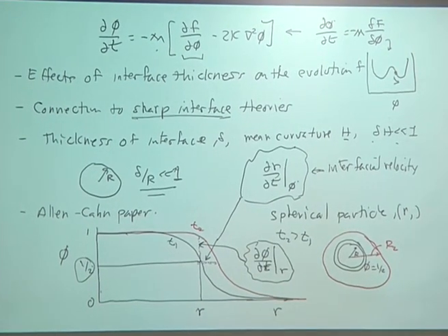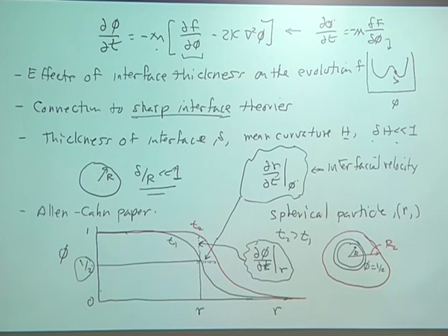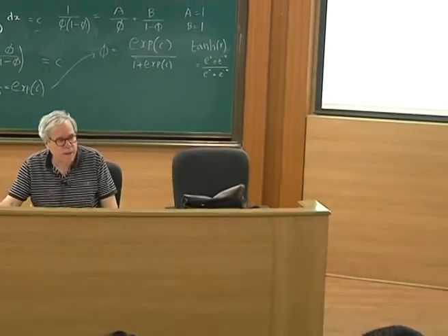Whereas in the conserved case, it doesn't depend upon the point-wise, it depends upon spatial gradients. So it's a mass flow problem. And so, in fact, you can have a system that sits there in the conserved case, and nothing happens. You quench, and the chemical potential is uniform, and nothing happens until you give it a little fluctuation. Okay?